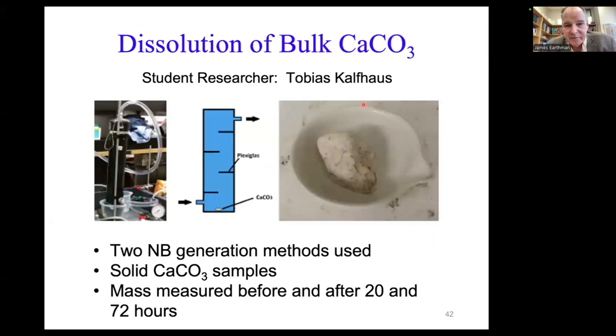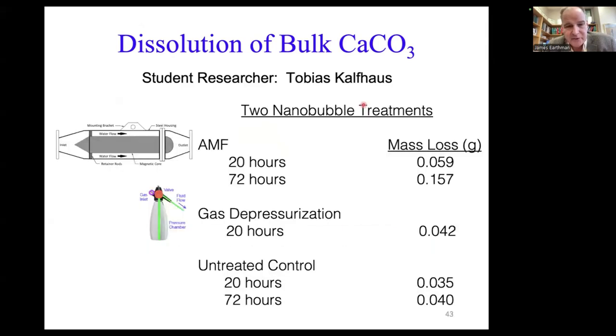All right, we did some experiments to check this. Here we took some solid calcium carbonate. We added DI water. We put DI water in this. We put nanobubbles in some of our experiments. We had untreated controls, and after 20 hours, you can see the mass loss of the calcium carbonate was 0.059 here. For the untreated control, it was 0.035.